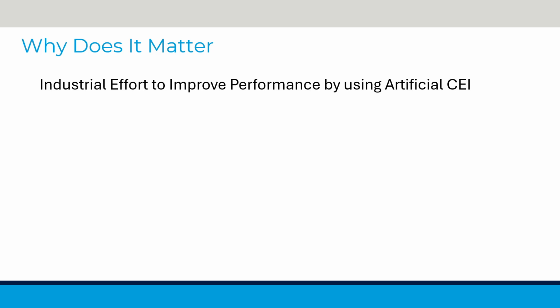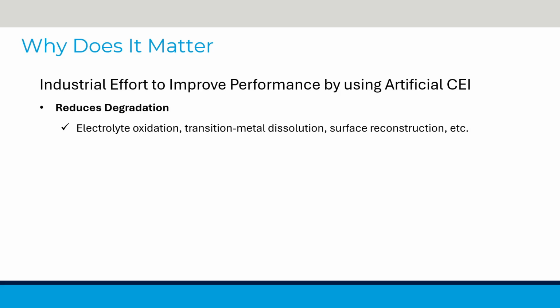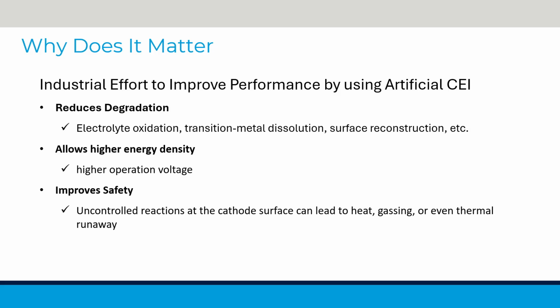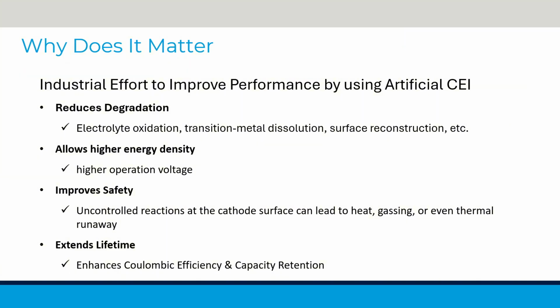This patent represents an industrial effort toward the beautifully detailed development of artificial cathode-electrolyte interphase. A carefully engineered CEI helps reduce the degradation, including electrolyte oxidation, transition metal dissolution, and surface reconstruction. With minimized material degradation, the cell can achieve higher operation voltage, thus higher energy density. With less uncontrolled reactions at the cathode surface, there's less chance to get gassing, heat, or thermal runaway. Finally, by suppressing side reactions and minimizing irreversible loss of lithium or other charge carriers, the battery retains its capacity over many more charge-discharge cycles, resulting in a significantly longer operational lifetime.